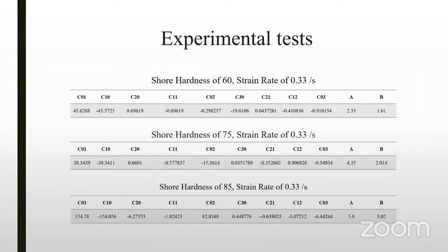As I discussed before, by following the procedures, we can calculate the 9 coefficients of the Mooney-Rivlin model and the coefficients of the dynamic increase factor. In these tables, we can see the calculated coefficients of the Mooney-Rivlin model from C01 to C03, and A and B, which are the coefficients of the dynamic increase factor for different shore hardnesses of the polyurethane at the strain rate of 0.33 per second.